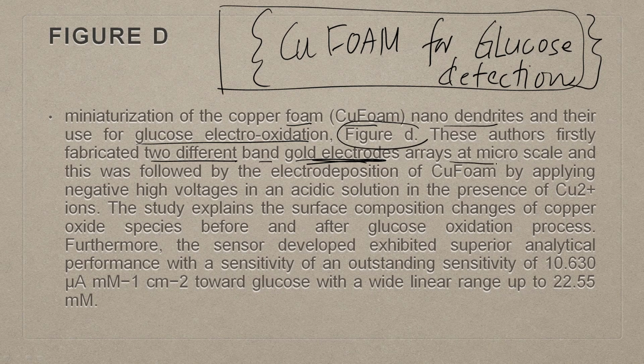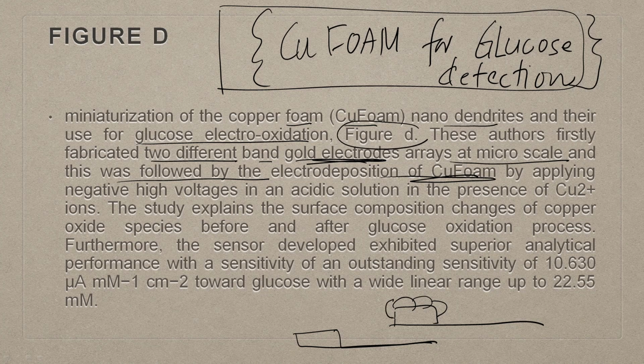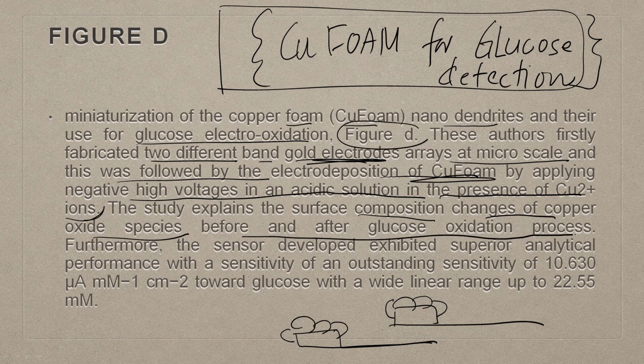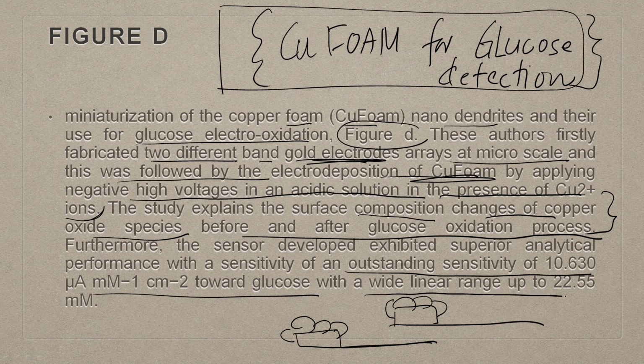So, gold electrode arrays at micro scale, and this was followed by the electrode deposition of copper foam. So, you have say for example, gold electrode lying there, on top of that you have these foams of copper, by applying negative high voltage in an acidic solution in the presence of Cu2 plus ions. The study explains the surface composition changes of copper oxide species before and after glucose oxidation process. Furthermore, the sensor exhibited superior analytical performance with an outstanding sensitivity of 10.6 microampere towards glucose, while wide linear range up to 22.5 millimolar.